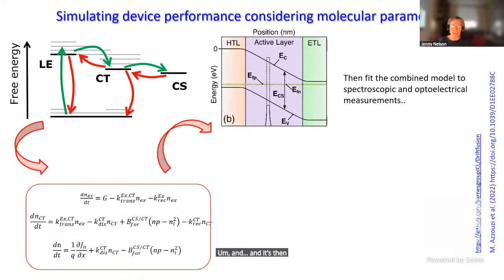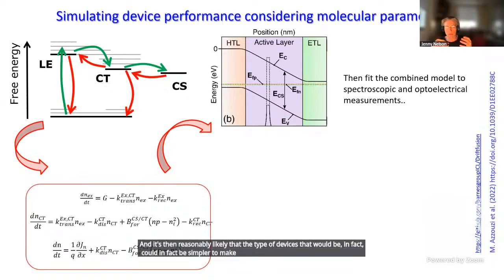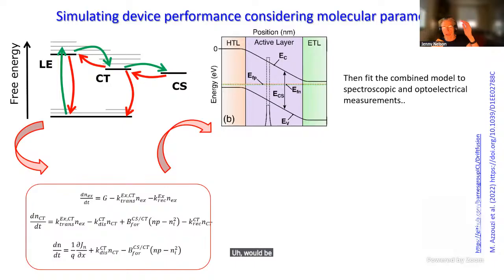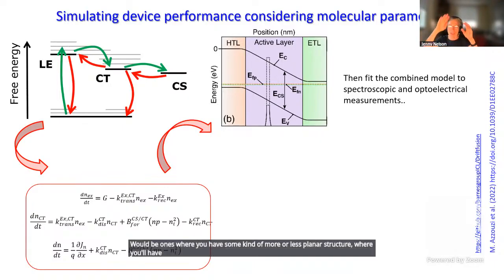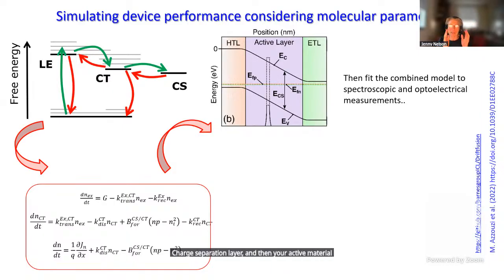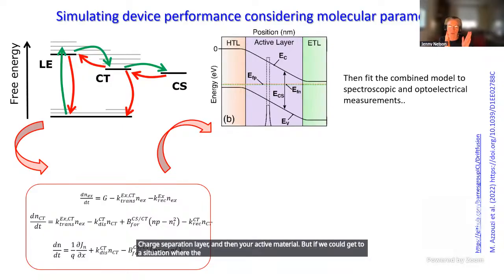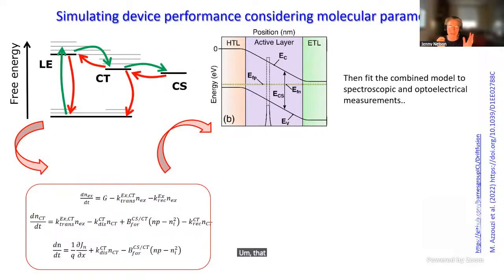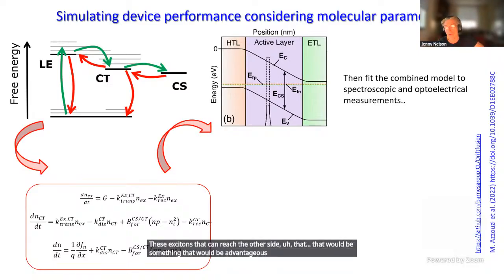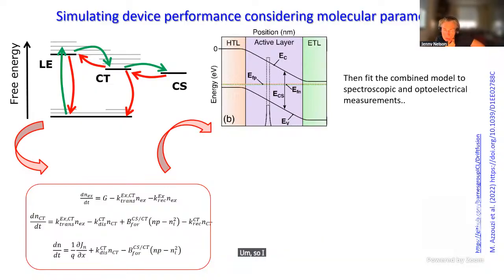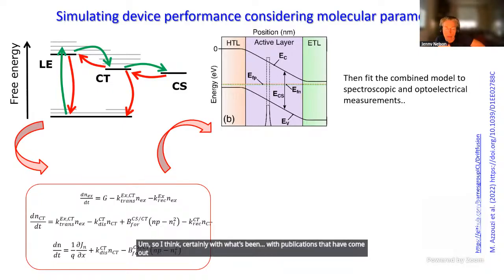It's then reasonably likely that the type of devices that could in fact be simpler to make or simpler to control would be ones where you have some kind of more or less planar structure, where you'll have maybe some charge separation layer and then your active material. But if we could get to a situation where the exciton diffusion length is long enough that your active material is able to absorb the light and then generate these excitons that can reach the other side, that would be advantageous, both from the point of view of voltage and from the point of view of the simplicity of the device. So I think certainly with publications that have come out recently, we see that things are going in that direction, more towards these kind of planar structures.